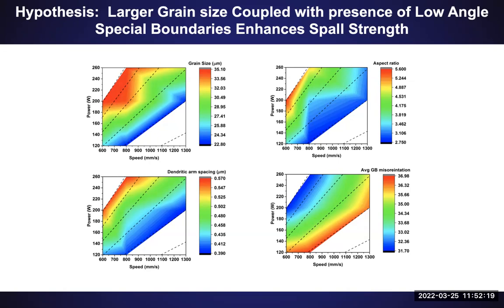One thing I would say is the statement that I made, that voids are nucleating at specific regions in the microstructure. You're pulling a region into tension, and within that volumetric region, there are features like grain boundaries and defects. Ten, fifteen years ago, that statement was quite controversial, because the strain rates you're looking at under this type of loading condition are like 10 to the 5 per second. So people would always say that you're overdriving the microstructure so much that it probably doesn't even matter. In the last 10 to 15 years, we have a better understanding of void nucleation. If you take the same material and work harden it, you're changing the void nucleation sites in the material, and that will change how many voids nucleate and where they nucleate in the microstructure. So does that help?